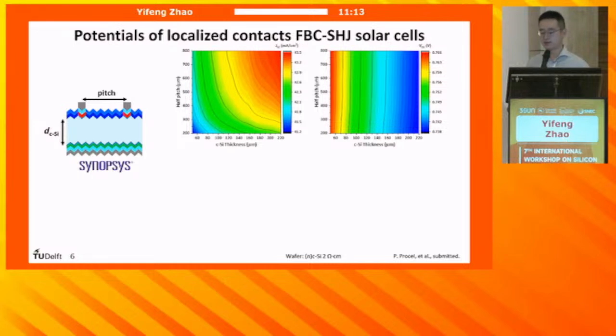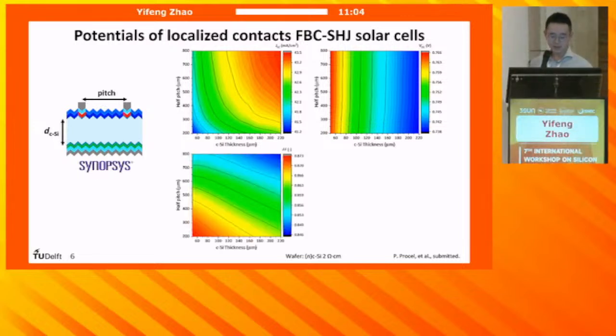And the higher VOC is ascribed to the reduced volumetric recombination due to the thinner wafer used. And then we look at fill factor. So the fill factor gets higher when you use thinner wafer and also when you use a smaller pitch. And in fact, the fill factor trend reflects that the vertical transport of electrons is affected by the wafer thickness, while the lateral transport of the electrons is affected by the pitch. And in this case, both effects have comparable level of influence on the cell fill factor.